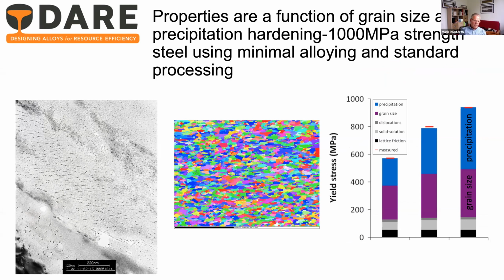And when we put that together and generate a very fine grain size as well, then you can see the contributions to strength that we get out of the different contributing factors. So at the bottom right there, you have the black, which is the basic strength of pure iron. Solid solution strengthening is small, but it's important. Dislocation strengthening is almost non-existent. And then the two main contributors here are grain size. And you can see this massive contribution to strength from precipitation, which is 500 megapascals or so, which is an absolutely massive amount, particularly for a steel.